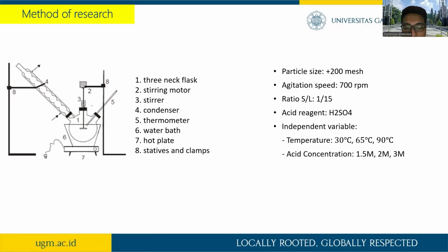After the leaching process, a filtering process was carried out to separate the filtrate and residue using a vacuum filter. The residue obtained will be dried in an oven while the filtrate will be measured in volume. The product is analyzed to determine the REE content using ICP analysis, and the residue is analyzed by XRD analysis. Samples of leaching results will be taken and diluted using demineralized water. The diluted sample is homogeneous. The diluted sample is filtered using a sand filter to avoid the presence of impurity solid and is ready for analysis.